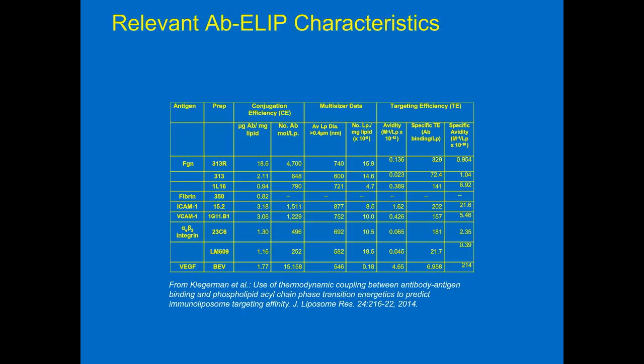What we do, of course, is this Immunoblot Assay. But first I should talk about how we purify the liposomes. We've used a number of different methods for that. The first method we used was gel chromatography. You could use a Sepharose column, put your liposomes through the column, and then you can separate by size.